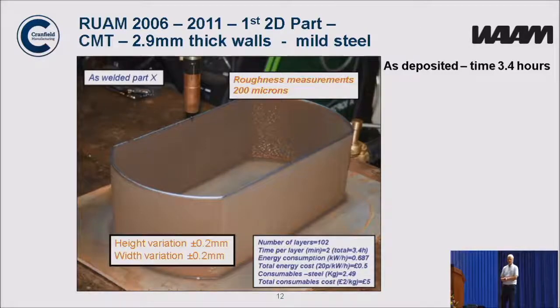And you can see it looks pretty good. It's a very simple steel part, and the cost of manufacture, actually, if you ignore the cost of the system, was £5. And it took 3 hours to build, and you can see that it's pretty accurate. We have a height variation of 200 microns and a width variation of 200 microns and a similar surface roughness.